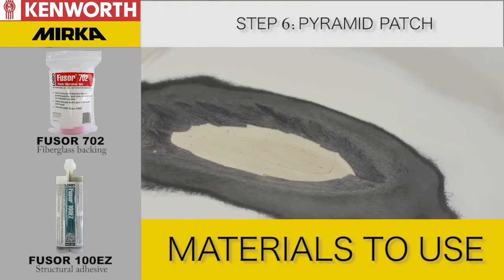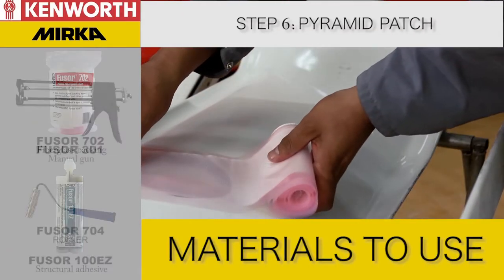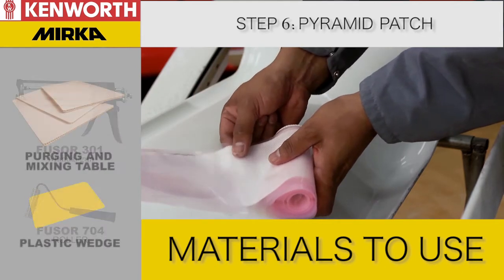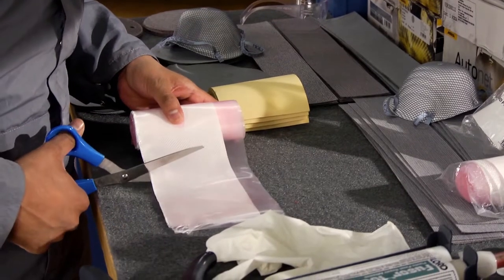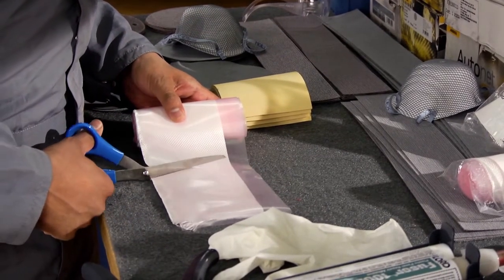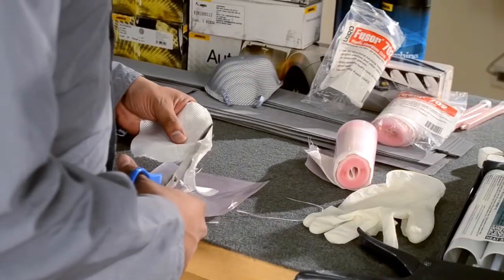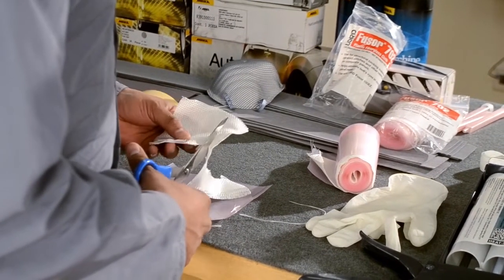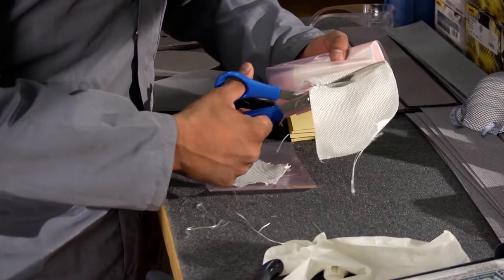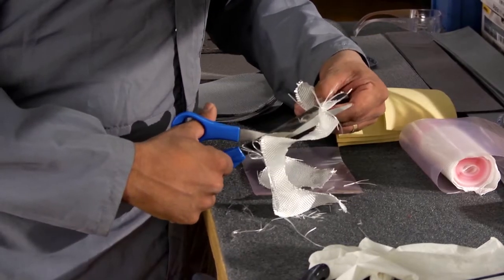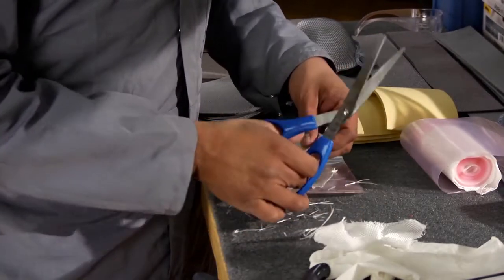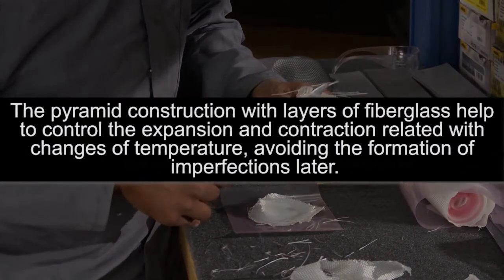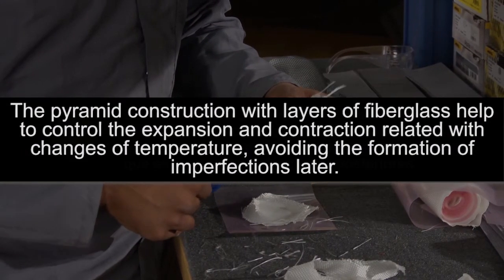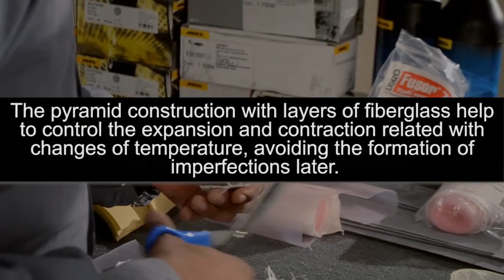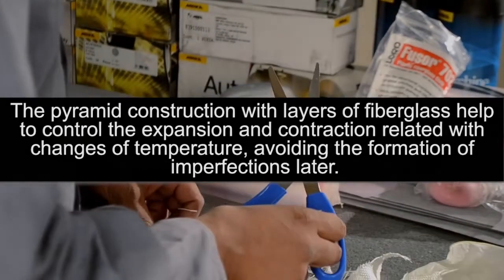Step 6. Pyramid patch. In Class A repairs and compound panels like Metton, SMC, and TPO, make a pyramid patch using fiberglass. Cut a piece of plastic that is approximately 1 centimeter larger than the damaged area. Cut pieces of fiberglass cloth consecutively that will be larger and cover the previous one. Layer the slightly smaller ones to go into the opening of the damaged area to repair. The pyramid construction with layers of fiberglass helps to control the expansion and contraction related with temperature changes. This avoids imperfections from forming later.